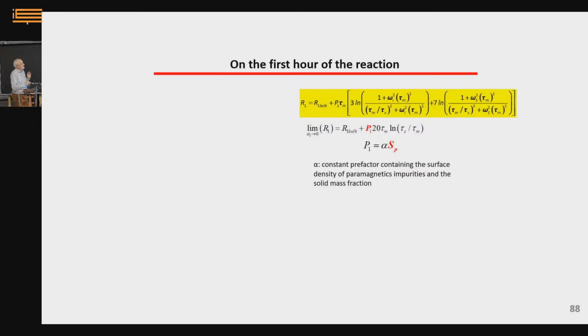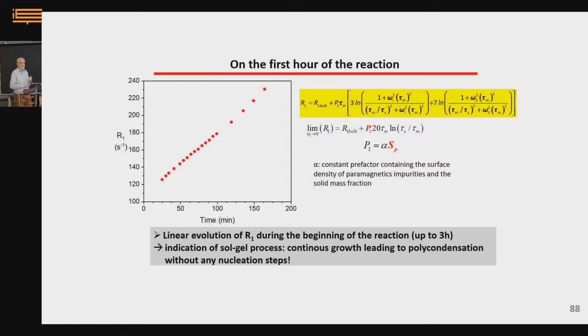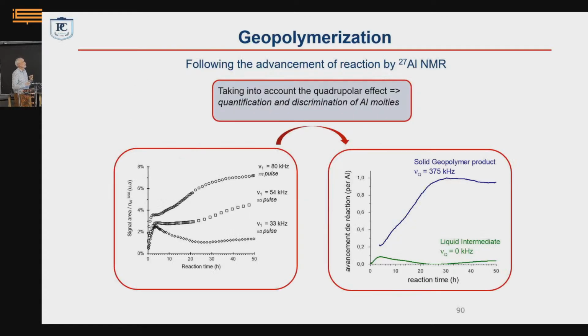And what's important is that you have characteristic times that describe the interaction of the molecule of water with the surface, but you have a prefactor that corresponds to relaxivity and is proportional to the surface area. We don't know the proportionality constant here, but what we are measuring is proportional to surface area. So we can follow development of surface area with time at relatively short time. Well, we need time to prepare, put it in the relaxometer and so on. But you see, even during the first hour, we still have this linear development of surface area. So the whole mechanism is linear. With those two NMR methods together, we are able to bridge this little gap here. And everything looks as if the process of the N-A-S-H gel formation is constant with time.